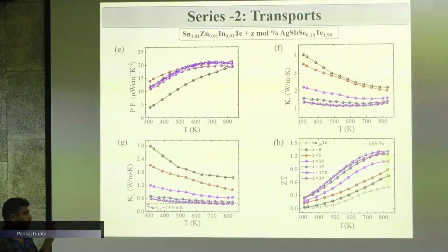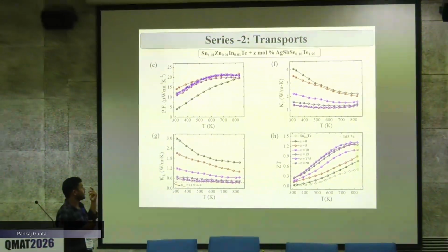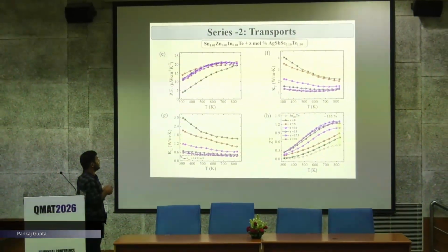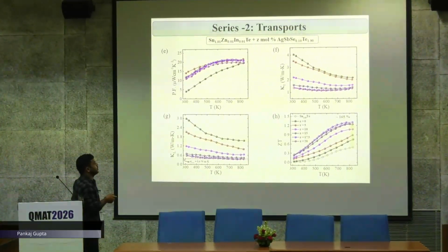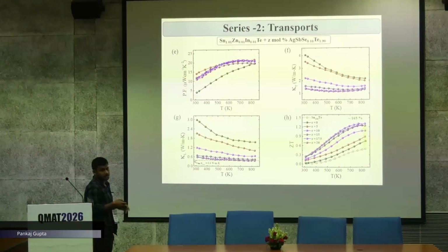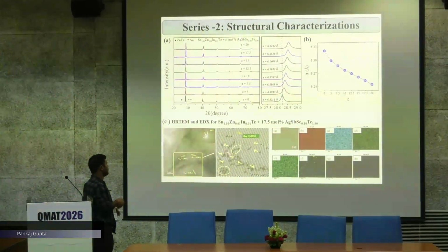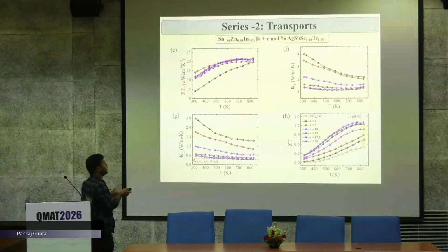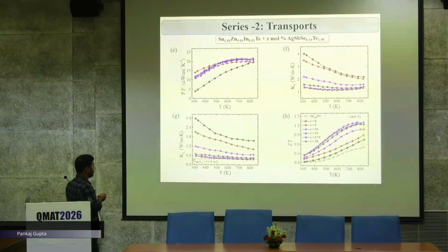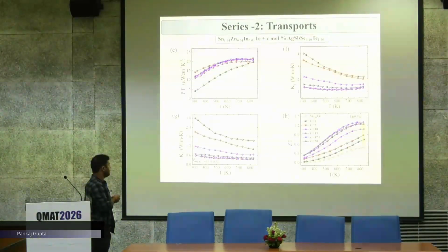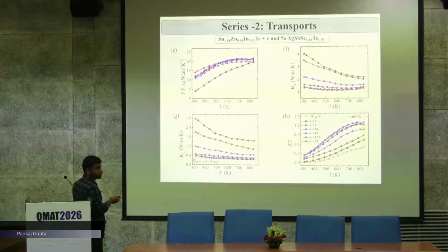And power factor is nothing but a product of electrical conductivity and Seebeck squared, and hence it is pretty high throughout the temperature range. Thermal conductivity is going to be low because of the high disorder, which we can see from here. High disorder is going to scatter more and more phonons, hence we can get very low thermal conductivity. We tried to segregate the lattice part using the same Wiedemann-Franz law, and we found it has approached nearly the amorphous limit of the sample.